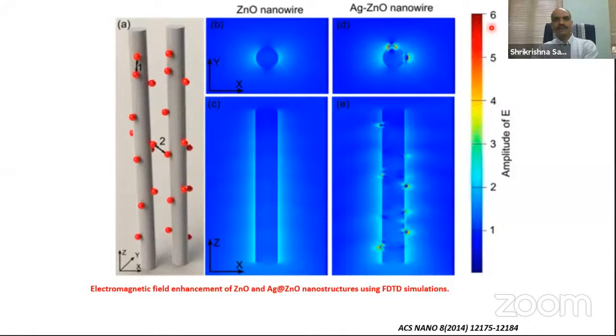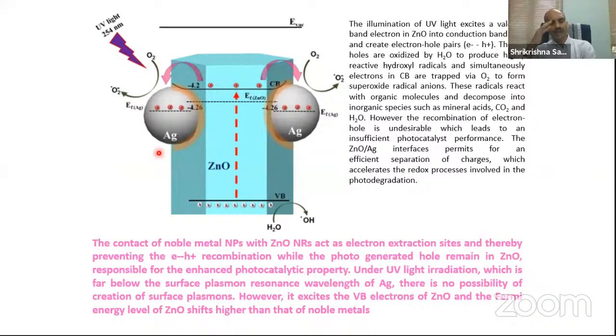But what happens when you have this silver nanoparticle? I make this, methylene blue, I have detected. Then I put on these UV radiations. All of you are aware that zinc oxide is a well-known photocatalyst. I mean, zinc oxide, you can have TiO2 or anything which is photocatalytically active material.